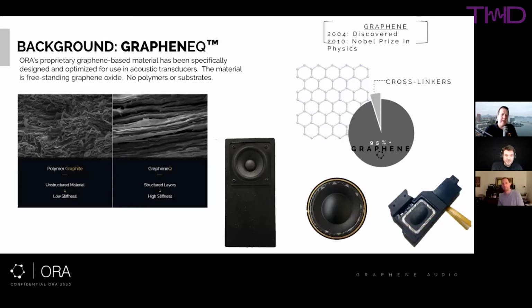Okay. And so graphene is conductive on its own? Pristine graphene is very conductive. When you add the oxide layer with our material, it ceases to be particularly conductive. But there are ways that you can restore that conductivity by a process called reduction, where you remove the oxygen again from the formed graphene material. So there are ways to treat one of our membranes to restore conductivity to a limited extent. We've toyed around with this to help tune the thermal conductivity of the material, but the electrical conductivity is still fairly low.